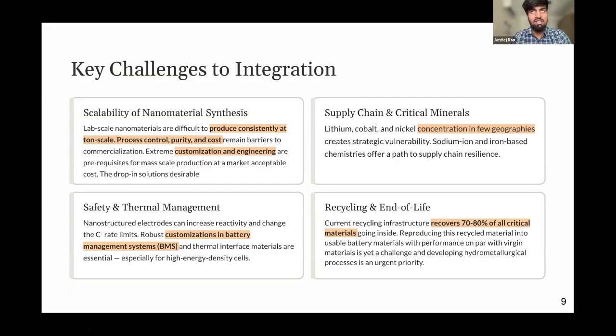Another challenge is that these chemistries still use critical materials: lithium, cobalt, nickel. They are not going to go anywhere because we depend on these materials for the chemistries, like even sodium ion, even lithium sulfur, even solid state, even lithium ion. We have to be dependent on these materials, and these materials are concentrated in very few geographies. Say, cobalt comes from a very small region of the Congo Republic, and we've all heard of certain atrocities happening with the laborers over there in the cobalt mining. Lithium, most of the lithium mines are owned by China as of now. So all the materials route through China to other countries. So we need supply chain resilience there too.